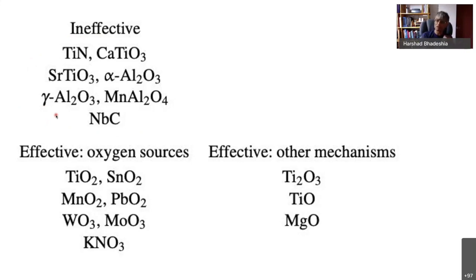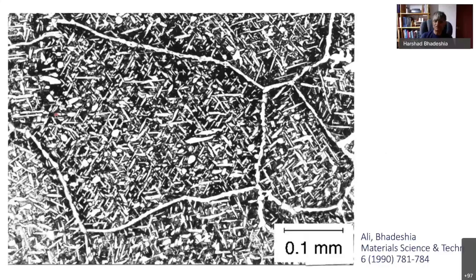Let's see what the microstructure should look like. Here is an example. These are austenite grain boundaries covered by layers of allotriomorphic ferrite. And these are plates of ferrite that have nucleated intragranularly within the austenite grains on some sort of heterogeneity like an inclusion. This is quite important in the sense that if a crack is propagating across this material, it will encounter many different crystallographic orientations of ferrite. Effectively, you are making the material tougher even though it may be stronger.